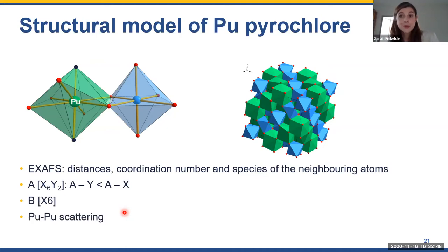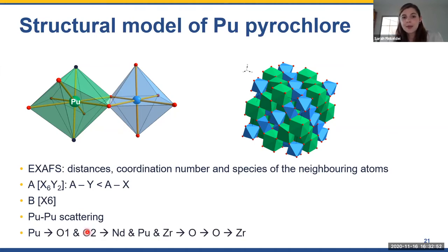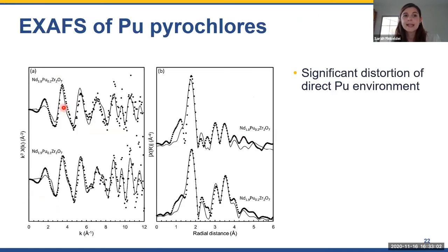Then we took plutonium scattering into account, and basically came up with all the coordination shells that would be surrounding the plutonium inside a pyrochlore crystal structure if it would be structurally uptaken on an A site. So here you can see the EXAFS of a plutonium pyrochlore, the k3 weighted EXAFS in the k and R space. What we observed when we fitted our data with those models is a significant distortion of the direct plutonium environment, which is not too surprising given that we have an oxidation state +4 on a usually +3 site, because neodymium is +3, and also plutonium +4 and neodymium +3 are different in their ionic size.